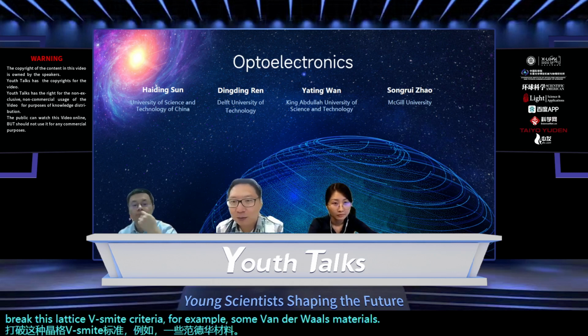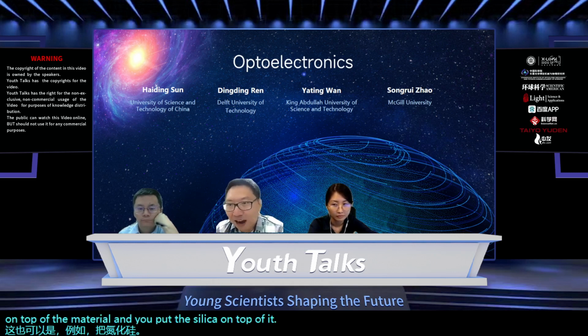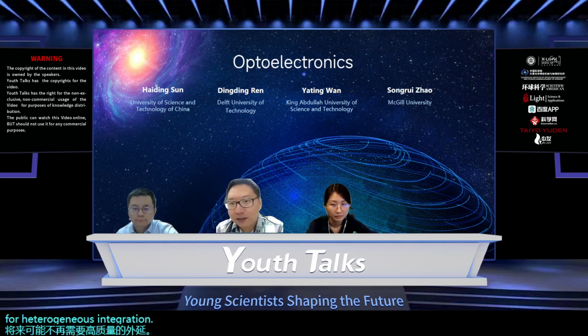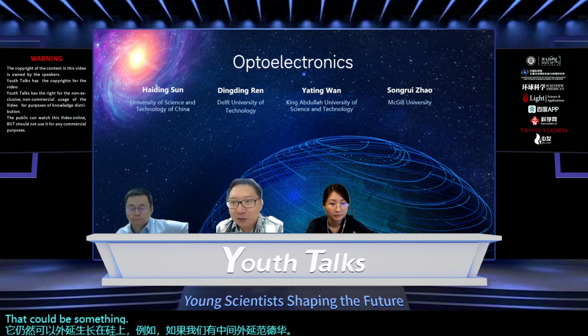You could, for example, put silicon nitride on top of a van der Waals material, and then put silicon, right, or another kind of material on that. So the lattice mismatch requirement for high quality epitaxy may not be a requirement anymore in the future for heterogeneous integration. For example, in GaAs, right? Or in lattice-matched phosphide, it could still be epitaxially grown on silicon, for example, if we have an intermediate epitaxial van der Waals buffer. That could be something to think about.